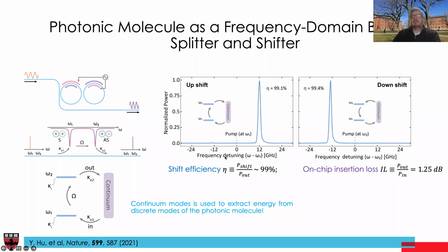So here is single-sided modulator experimental data. We make two ring resonators that have splitting of 12 gigahertz. We put light originally in one of the resonances, turn RF on, and RF is on all the time. But if you dial in an appropriate amount of RF power, all of the light from this resonance ends up here with 99% efficiency. And what's really interesting, the process is reversible. So if I put light at this resonance and apply RF, all the light ends up here, as shown here. So you can use this to swap two channels. So you can think about it as a single-sided modulator.